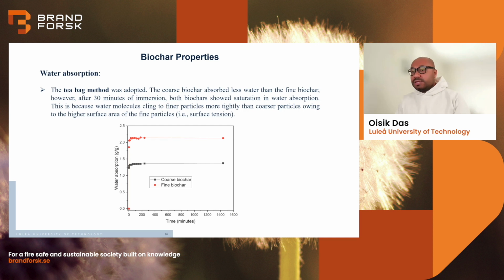in a tea bag, and then we put it in water, and we measured the weight change at regular time intervals. So what we see from the graph is that the fine biochar, the one made from wood with smaller particles, absorbs more water compared to the coarse biochar. And this is because fine particles, because of the smaller size, the water molecules attach to these small particles, and the small particles have more surface area. That's why the water absorption of the fine biochar was higher than the coarse biochar. But what we see is that after about 30 minutes of immersion in water, both biochars reach saturation.